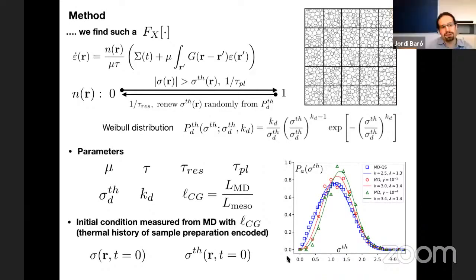I mean, you use this Weibull distribution for the threshold. Yes, this is the Weibull distribution. It is used for when you have a plastic event: you should renew your local threshold with a new one. But in the beginning, for having the transient, we inject what we measured from MD.